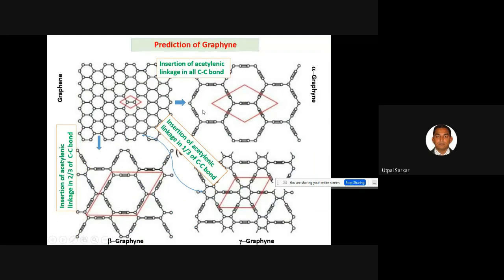Now, this is graphene, and if you insert the acetylene linkage between the two carbon atoms, then three different possibilities mainly come. One is that if you insert one third of the acetylene linkage, there are 6 bonds and alternate bonds are broken and the acetylene linkage is inserted in these positions, so you will get this gamma graphyne. If you put two-thirds of the acetylene linkage, like here, then you will get beta graphyne. These structures are different. If you put the acetylene linkage in all these carbon-carbon bonds, then you will get alpha graphyne. This is basically an enlarged version of graphene where between two carbon atoms you are seeing an acetylene linkage.